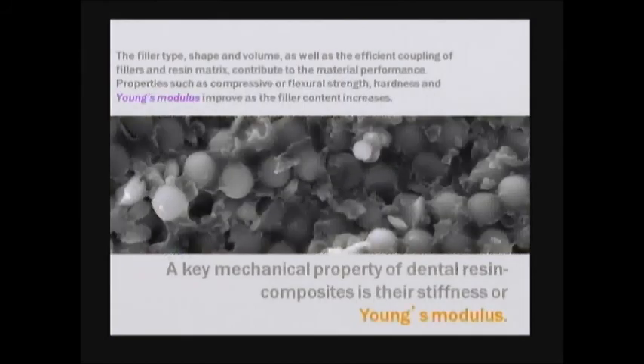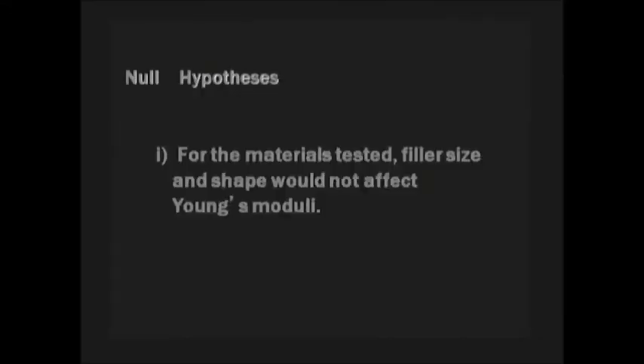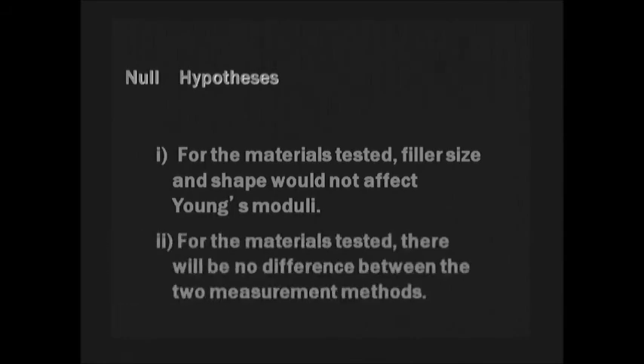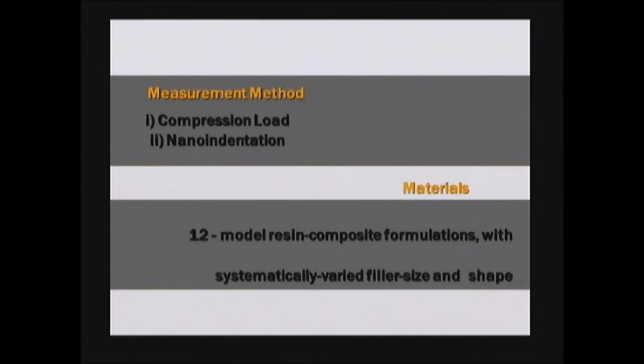So in my first part of research, I'm going to focus on the Young's modulus as a property that we studied there. So in this research, we wanted to measure the Young's modulus of a series of these model polymeric materials. And the two parameters that we investigated were the filler size and the filler shape. So our first hypothesis was that filler size and shape would not affect it. And the second one, there's no difference between the two measurement methods that we used. So in this one, the two methods that we had, the first one was compression load, and the second one was nano indentation. In total, there were 12 formulations, and these are the formulations.